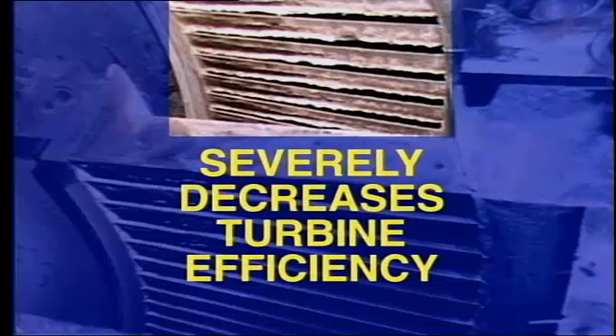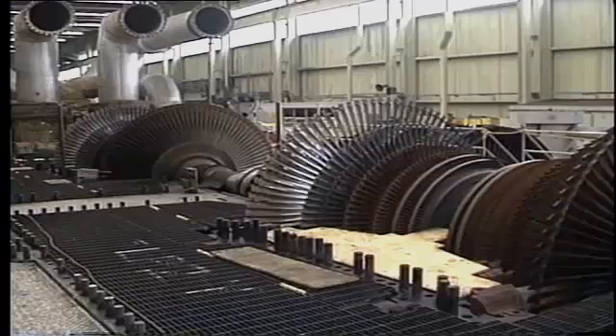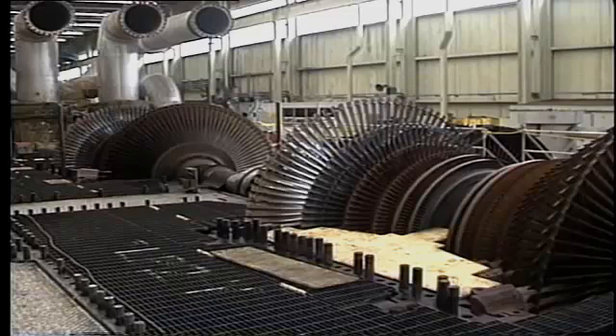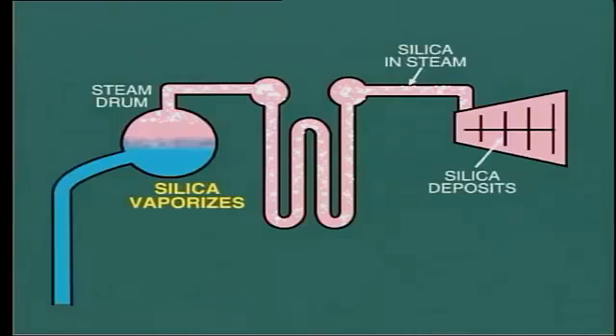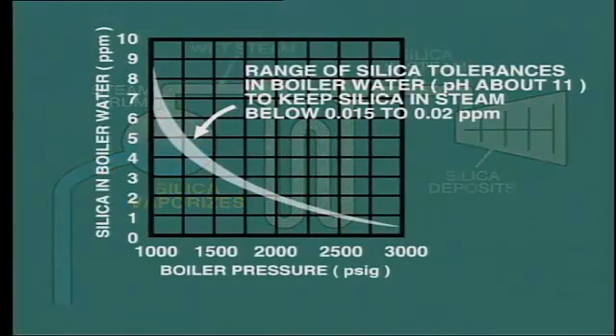Silica, of course, is the material which we find in sand and is used as the main ingredient in making glass. The silica deposit on turbine blades is just as hard as glass and extremely difficult to remove. The effect on an operating turbine is to change the profile of the blades and severely decrease the efficiency of the turbine, as well as reducing the output. The only cure is to shut down the turbine, remove the rotor, and mechanically clean the blades, usually by erosive blasting with a material such as aluminum oxide. In order to prevent these deposits, it is most important to keep the silica content of the boiler water below a predetermined limit, typically 5 ppm on a 1200 psi boiler.